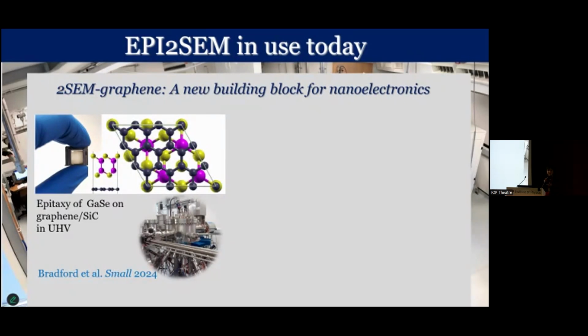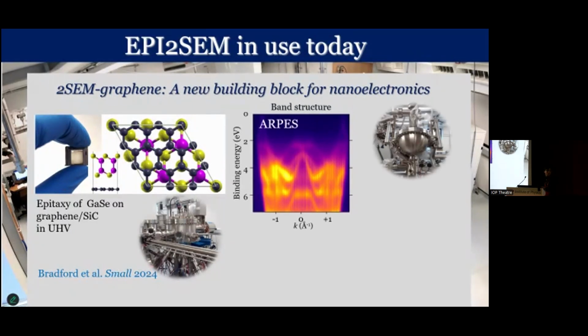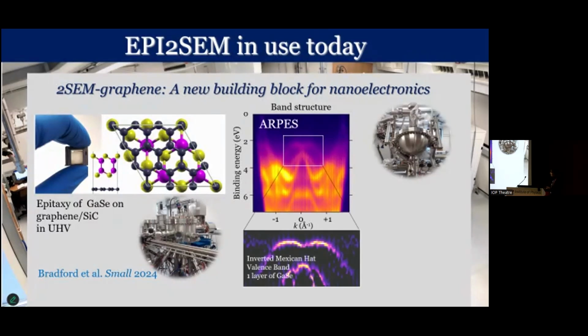And there is this van der Waals gap because the two layers do not interact. So we grow this system in UHV, then without breaking the vacuum, we move to the electron spectroscopy study, so we can visualize the energy dispersion of the electrons. We can see the band structure, and we can discover this very unusual dispersion. This is called an inverted Mexican hat type of dispersion with extremely flat dispersion corresponding to large electron mass.